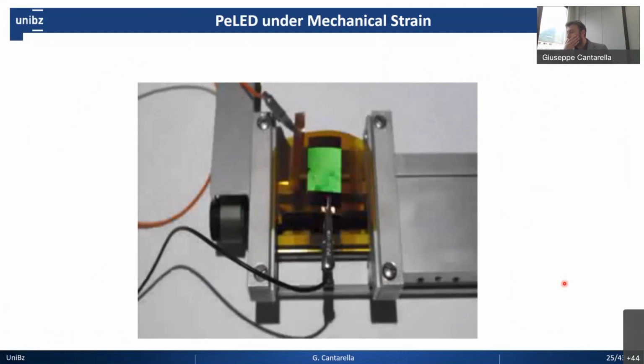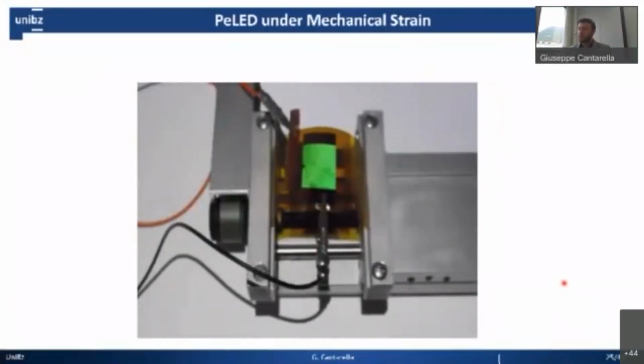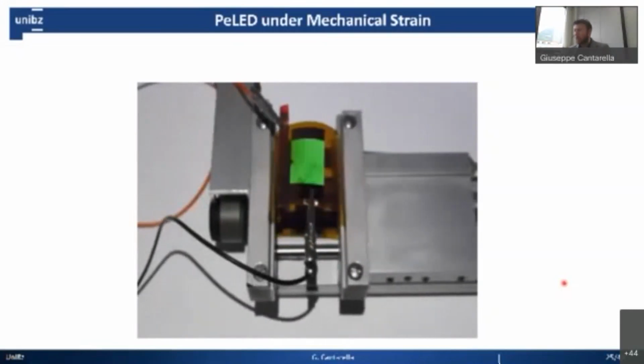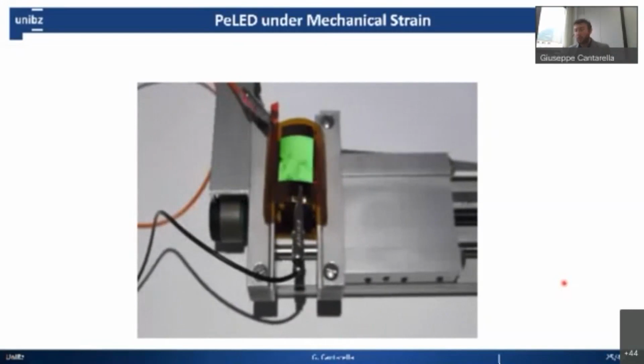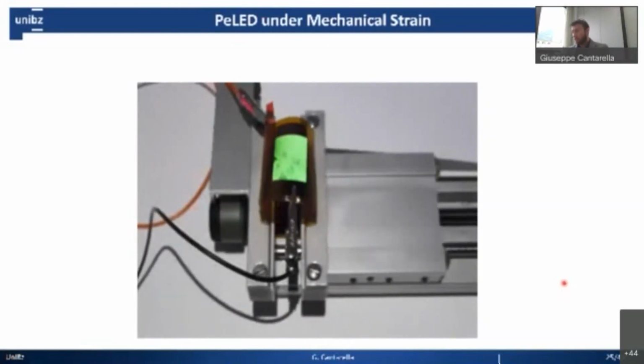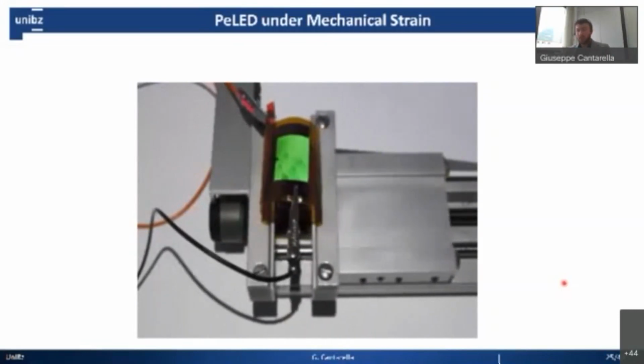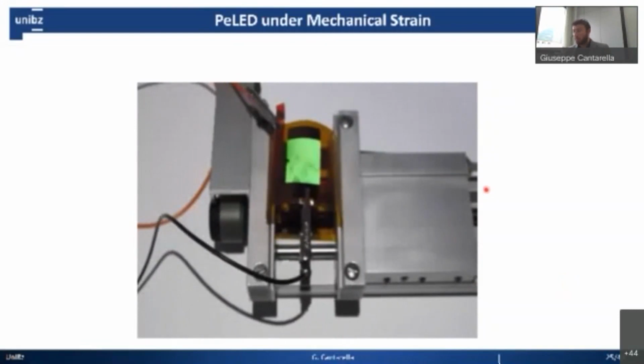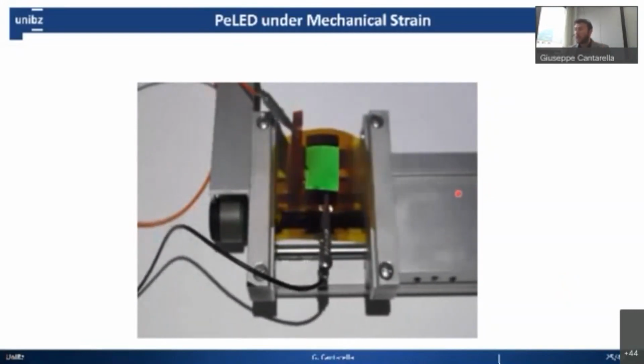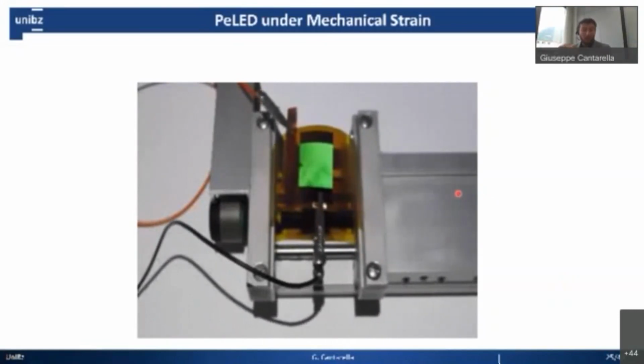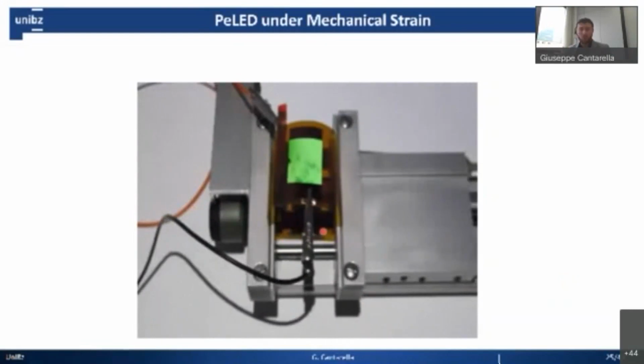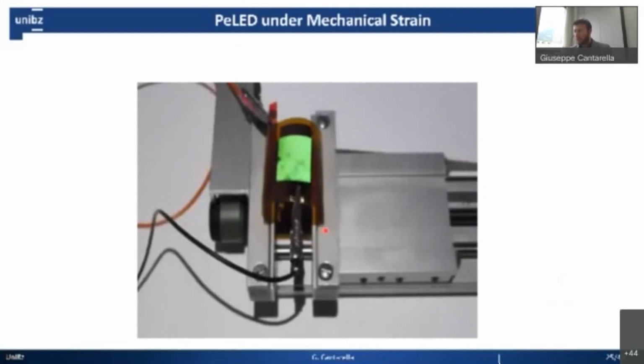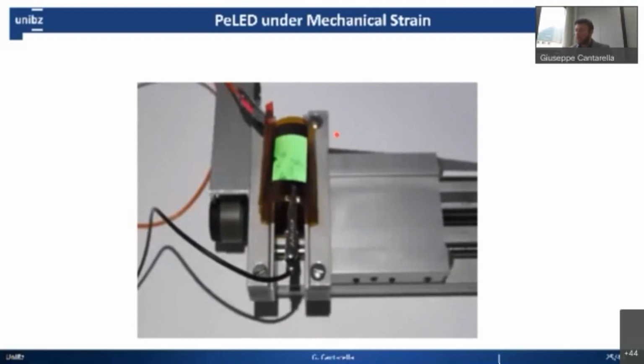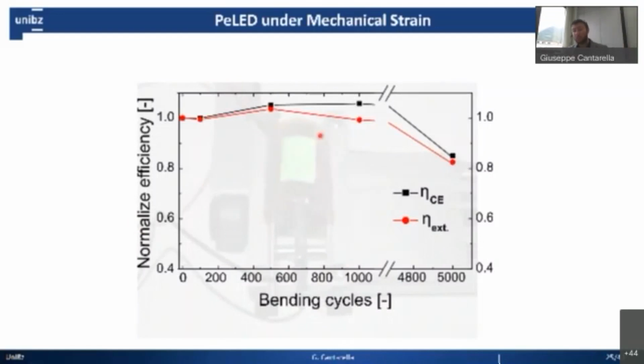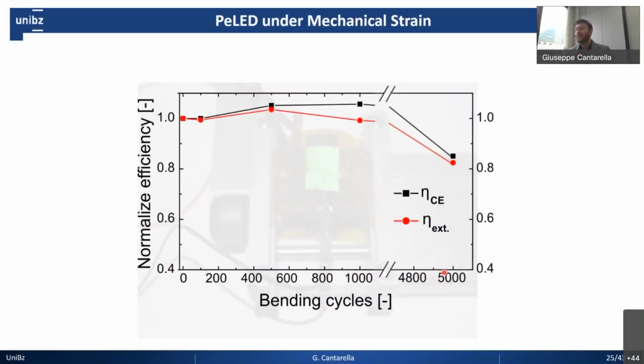What we also wanted to do, and that's the idea behind this video, was trying to make sure that our large area LEDs, so the ones in the centimeter square, could still be functional during a dynamic mechanical strain. So what you see is, at normal speed, the bending of a large area LED. The flickering that you see is due mostly to the non-ideal metallic contact that we have. But in general, our devices are still perfectly functional. And what we did with this device was just testing multiple times. So we did this bending down to 1 centimeter radius up to 5,000 times.